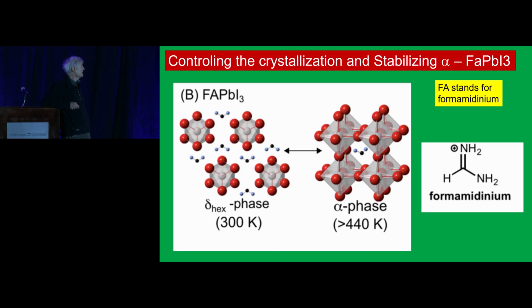And so you would like to use that, but the alpha phase is not stable. It has a phase transition at 160 degrees. So a photovoltaic cell that can only run above 160 degrees is valueless. And so you need something that works at room temperature, maybe up to 100 degrees.